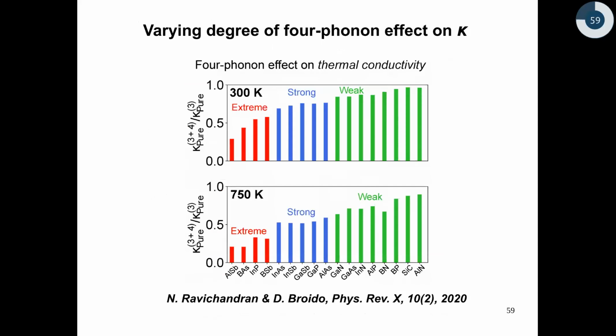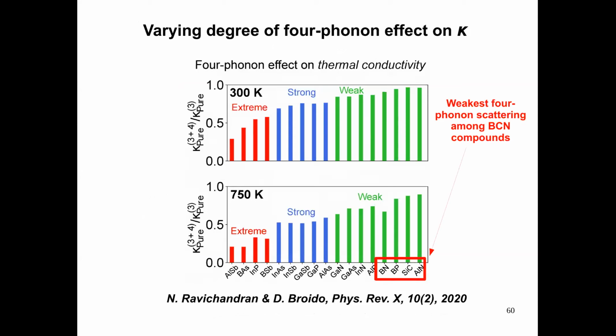So to give you a consolidated picture, here I'm plotting a histogram of the effect of 4 phonon scattering, that is K3+4 divided by K3. And you can see at room temperature, all the 3-5 compounds with the green bars have a very weak 4 phonon scattering. And there are a few candidates, including boron arsenide, which have extreme 4 phonon effect. Interestingly, we find that the candidates towards the right side, where the 4 phonon effect is weak, include BCN compounds. What I mean by that is these compounds are composed of boron, carbon, and nitrogen or some other atom.